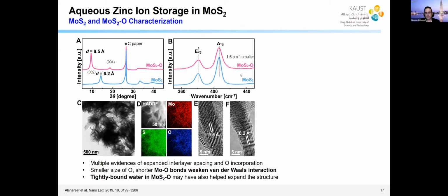This weakening is also reflected in this shift in the Raman spectrum. You can also see in the TEM at high resolution, this is the molysulfide by itself, 6.2 angstrom. But when you put in the oxygen substitution, you end up with 9.5 angstrom. So all this data proves that oxygen incorporation into the molysulfide expands the interlayer spacing.